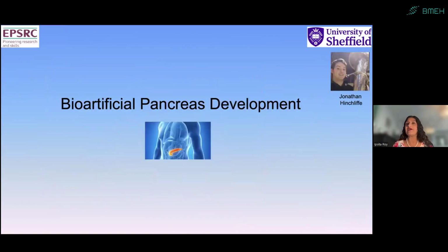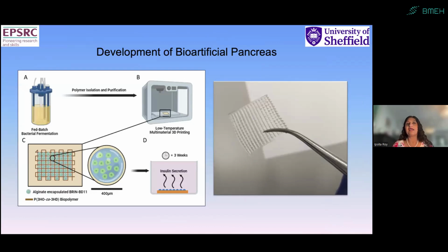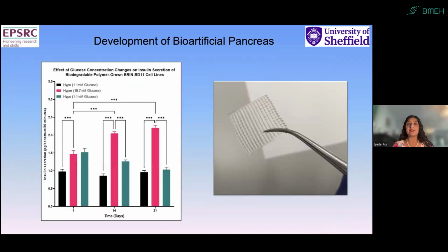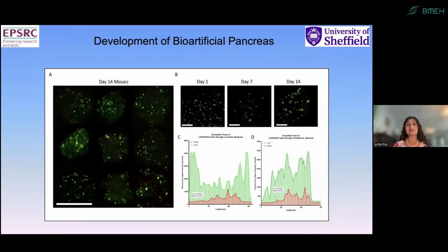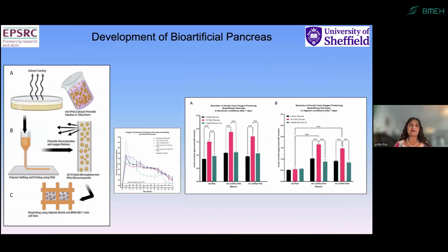We are also trying to develop bioartificial pancreas. Here again, medium chain length PHA has been used, and what we did was we seeded Brin BD11 cell lines. We co-printed them along with alginate, encapsulated in alginate, and we observed that these cells were producing insulin in a glucose responsive manner. And these were the cells on the constructs. As you can see, they're forming really nice agglomerates, which is typical of pancreatic cells.